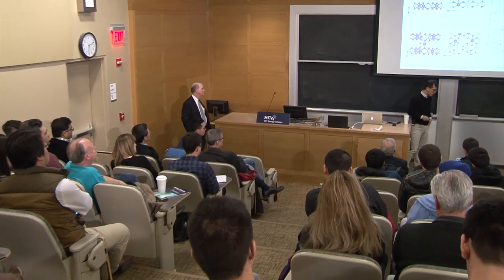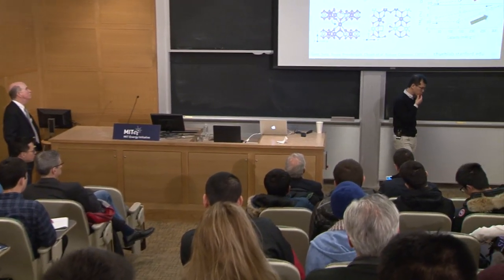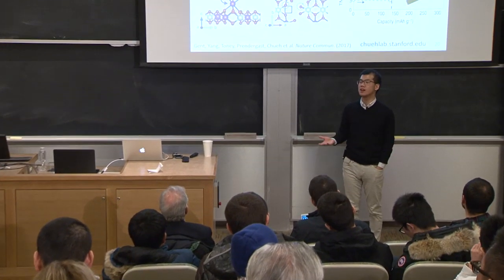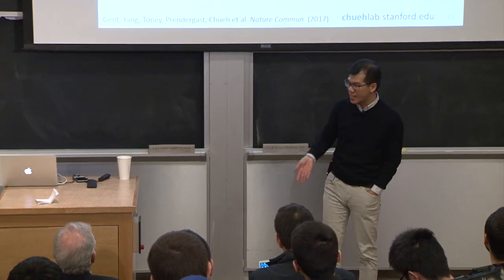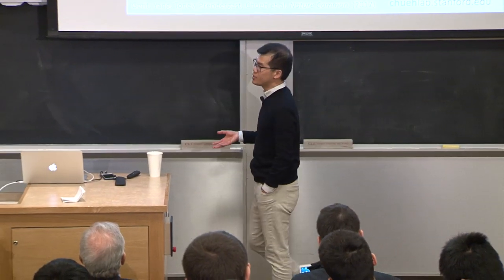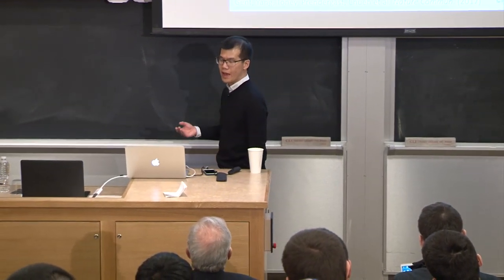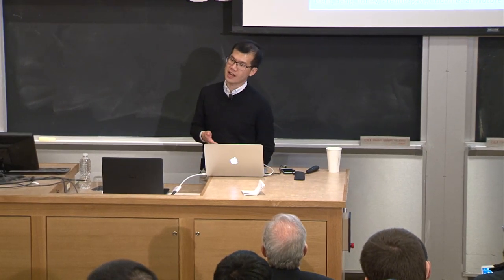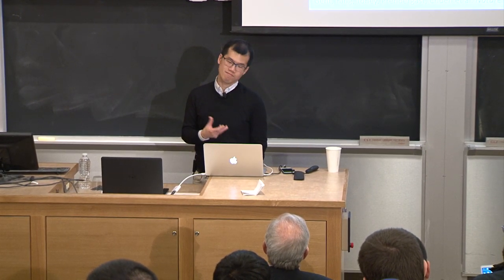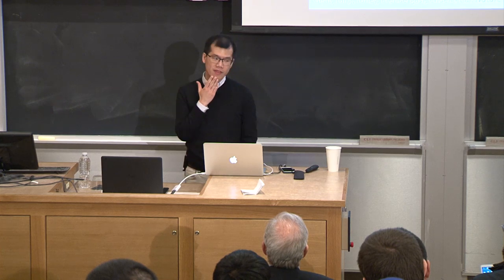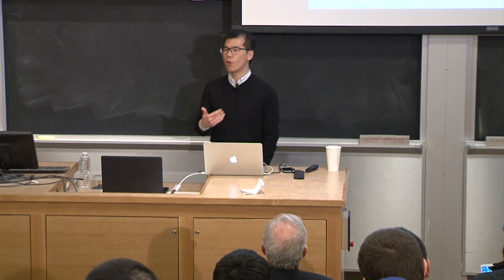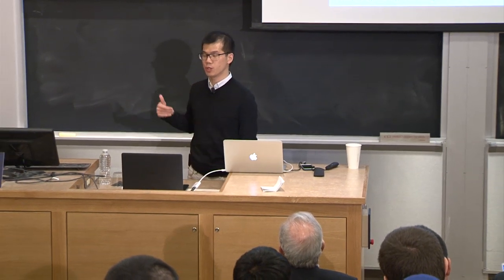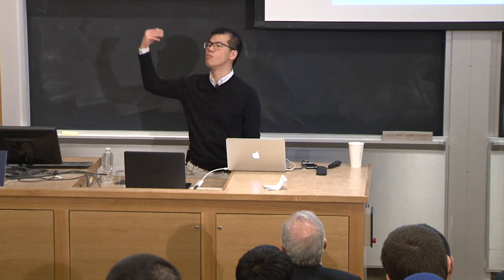Yeah, I think this is generally true for introducing point defects in a system: the lattice constant will change. So this is inevitable. These materials are relatively hard, so expansion and shrinkage is certainly a concern. But the good thing about batteries is they already undergo quite a bit of volume change as you remove and insert lithium. So this is not much more than that.